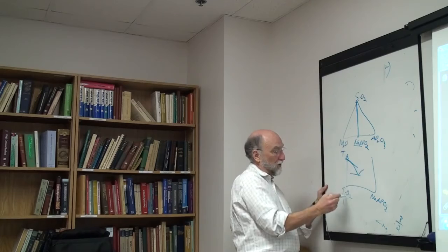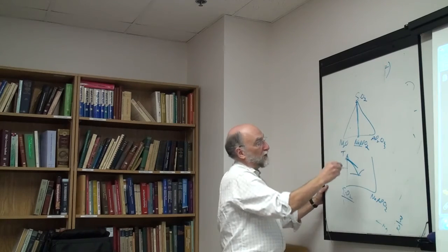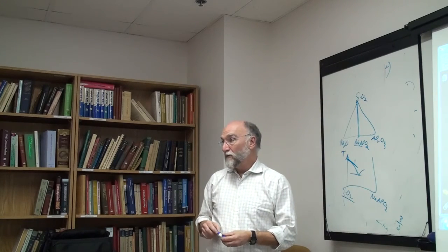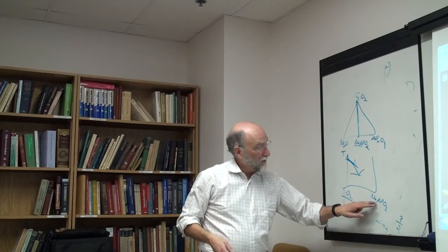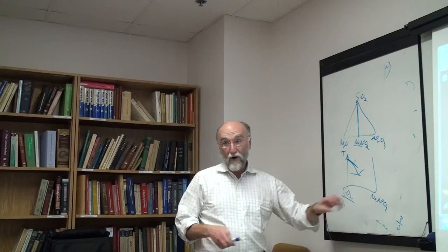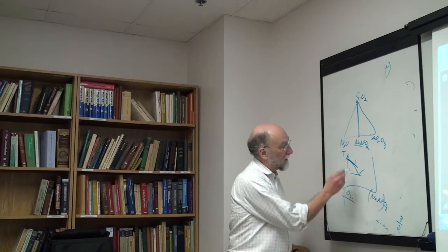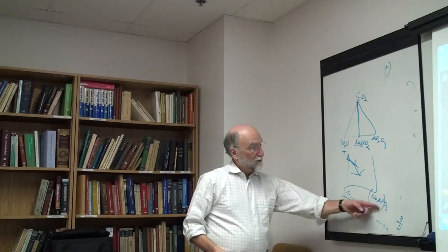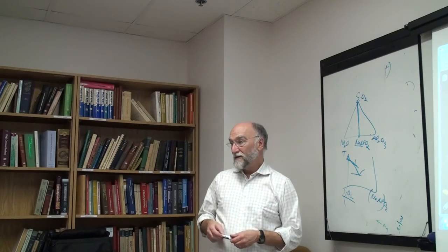You take the limiting slope here at this end, put it into that equation, and you get exactly a one particle slope, indicating that the sodium and aluminum are going in together as one particle. They are not going in as two separate particles, they're going in as one particle. This is right up to the end. The sodium and aluminum stay associated.